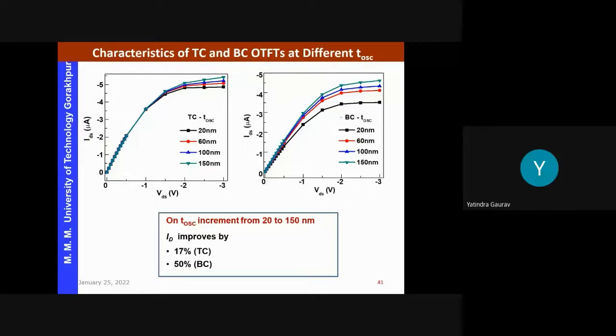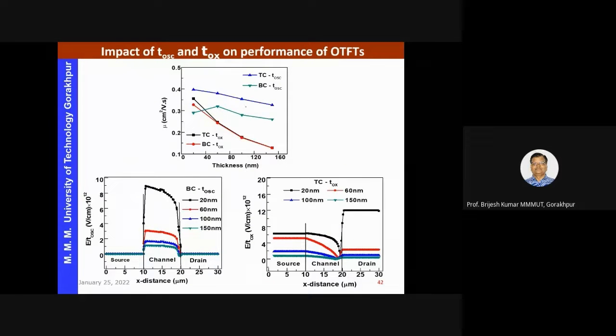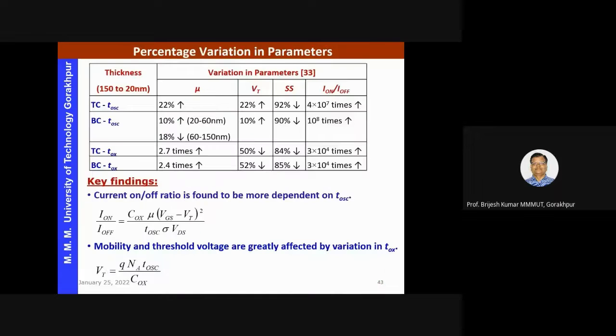So this comparison is reported in our paper. If we go for a comparison between both structures, top contact and bottom contact, here you can see, with OSC thickness increasing from 20 to 150 nanometers, I_D improves, right? Not only I_D but all parameters. But the I_D improvement in top contact is only 17%, whereas this has much more impact on bottom contact devices. Similarly, this performance parameter is the mobility comparison for both structures, top contact and bottom contact. Then we have analyzed the effect on the electric field. This comparison is given as variation in percentage.